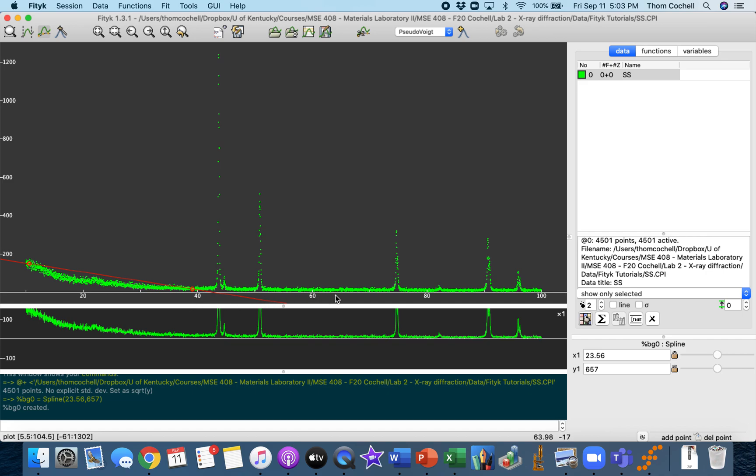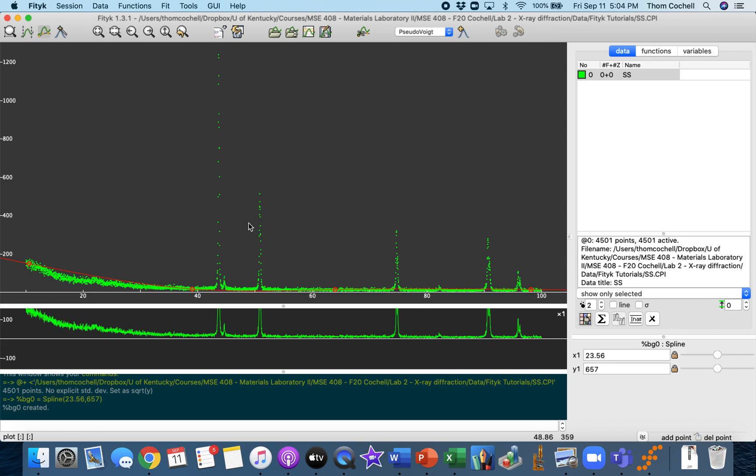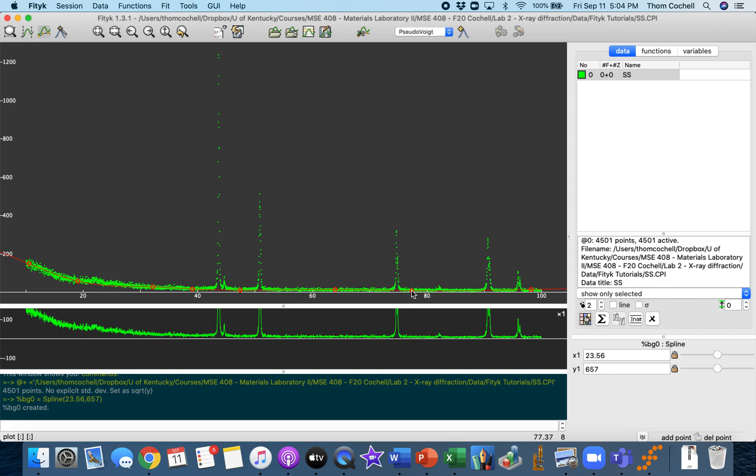Let's pick another one out here where there doesn't seem to be any peaks. You can see that it's brought it back in line, but it curves back down here again, so I'll pick one down here where there's no peaks. You can keep doing this, adding in until you've sort of made a good representation of the background. Here you can see that it's not really well fitting, so I'll add another point. You can add as many as you need. I do try to add as little as I can to get the fit that I want, but I also don't want to distort the data.